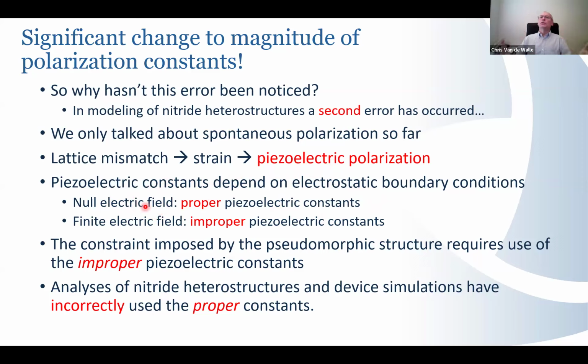And that's what you would get if you naively do the experiment where you have a freestanding material, you strain it by pushing on it, and you try to measure what the polarization is, which is typically done by measuring how much current flows as a result of the fields and charges that are being generated. So those are the proper piezoelectric constants. But those are not the ones we should be using when we model heterostructures. Because as I showed you, in those heterostructures, we actually have a finite electric field.